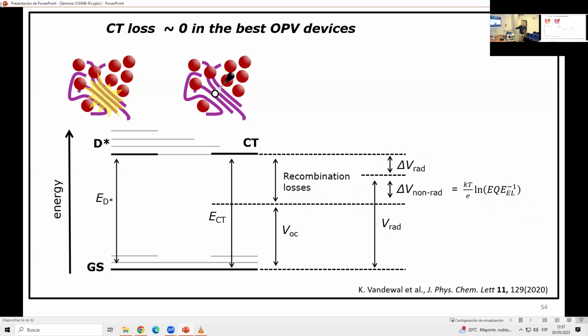This means this is the solar cell. If recombination happens, part of the recombination event will result in light emission, and part of it is non-emissive. Because the material absorbs light, the emissive part you cannot avoid, and the non-radiative part, people like to think you can avoid this, like in every solar cell technology. That's why silicon and gallium arsenide now have such high efficiency, because they manage to get rid of the defects and avoid all the non-radiative loss, and get a high VOC.